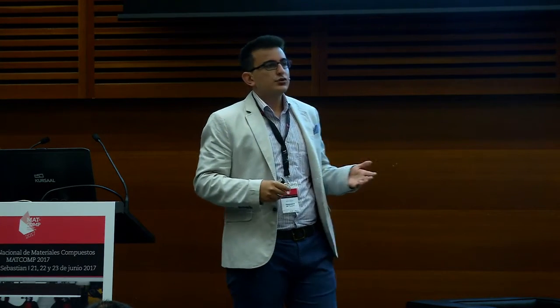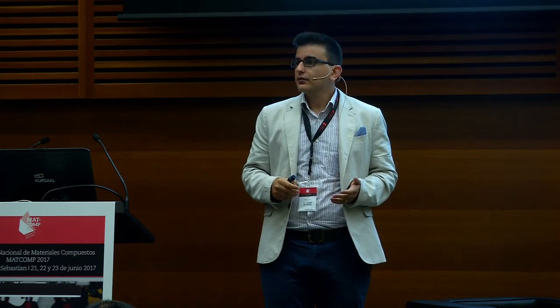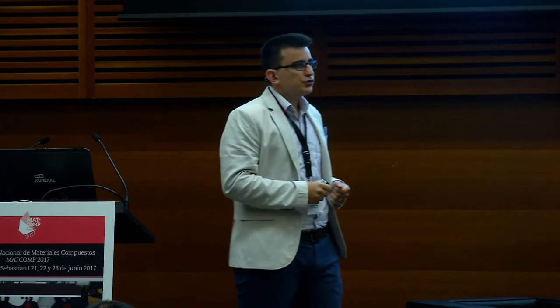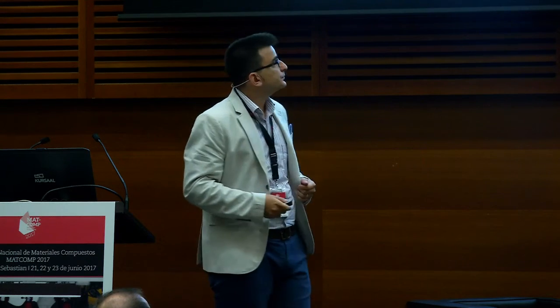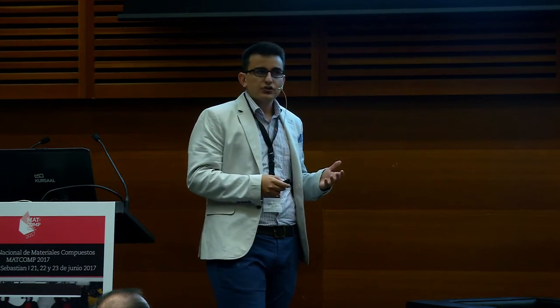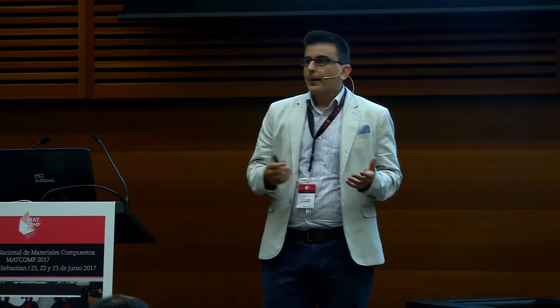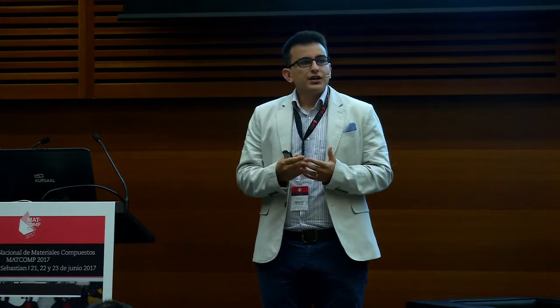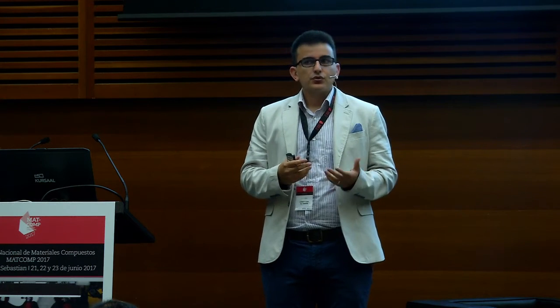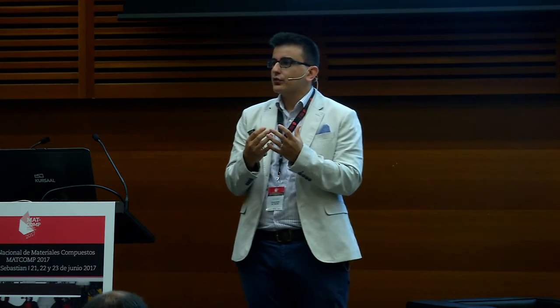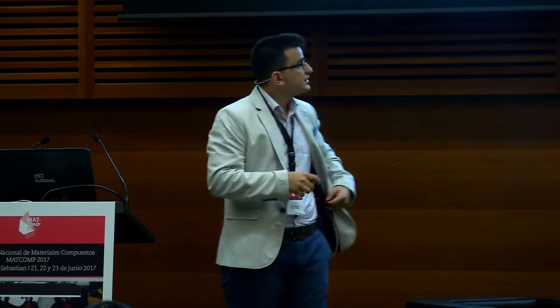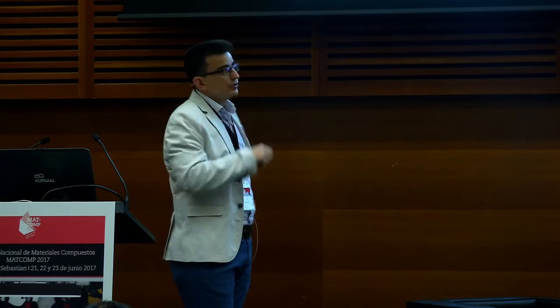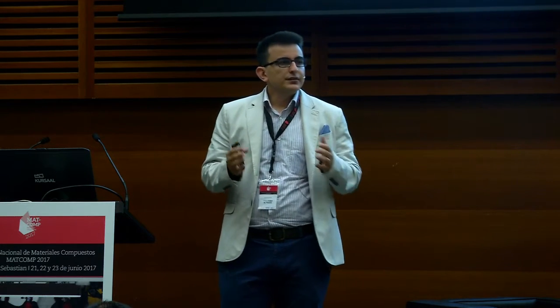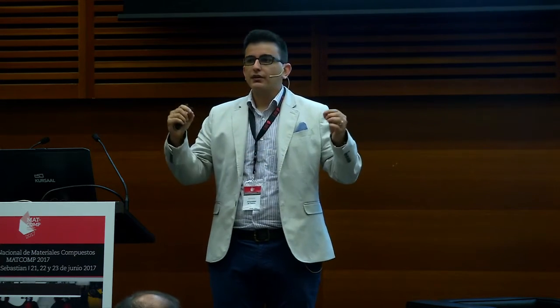And if we continue to the micro-CT analysis, we observed during our ongoing work 3D cracks and porosities. And these 3D cracks actually are taking place due to the highly excessive shrinkage of the resin-rich areas. So during processing, because of the chemical shrinkage, the resin shrinks more and separates from the fiber roving regions. That's why we have these through-thickness 3D cracks along the pulling direction. And it's amazing to see that these cracks are transforming. Their shape is changing because of this fiber misalignment.